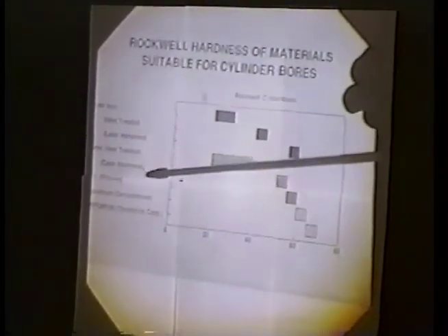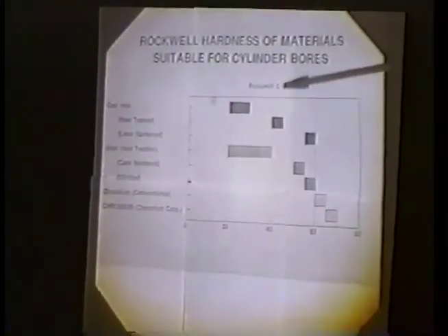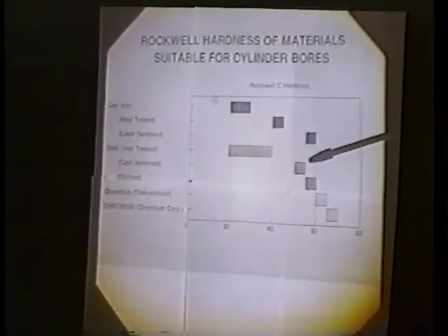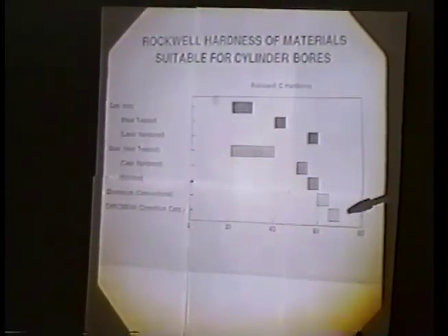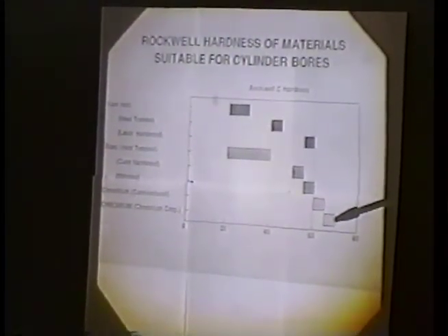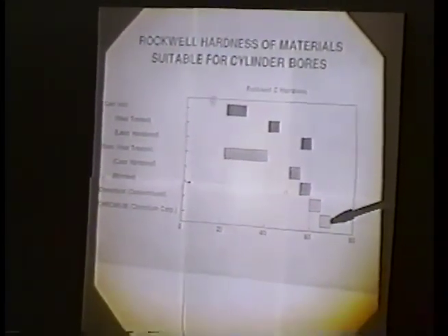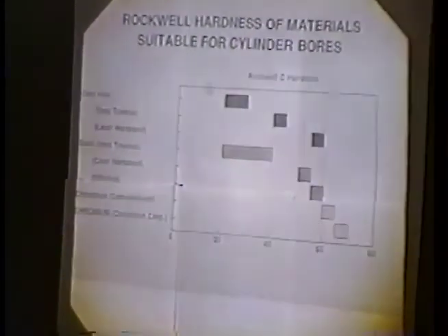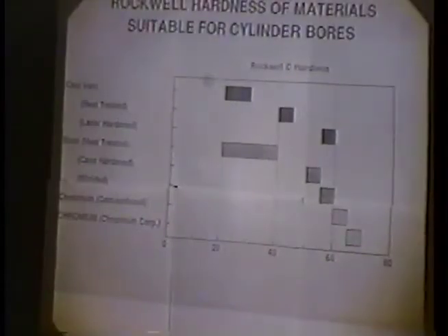Then you have the heat-treated steel, case hardened and nitrided, with those hardnesses out here in the 50 to 60 range. And then conventional chrome plate and our proprietary chemistry. The hardness of chrome can be controlled by the type of chemistry that you use in the plating bath itself.